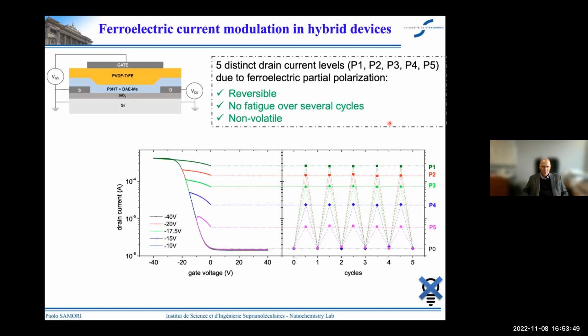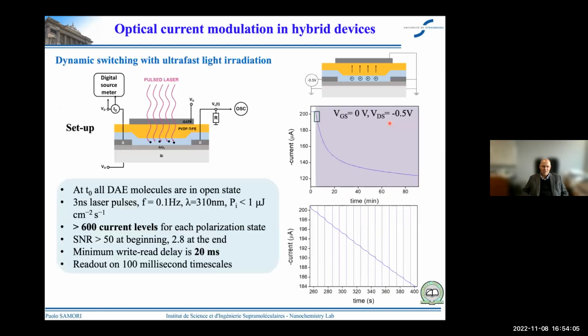What we have shown here is that we can access five distinct drain current levels, P1 to P5, due to the ferroelectric partial polarization, with high reversibility, no fatigue over several cycles, and no volatility. Then at that point, we need to show that in this kind of device geometry, we can still use the light responsiveness of the dielectric. And so we can shine light from the bottom, from the top, sorry.